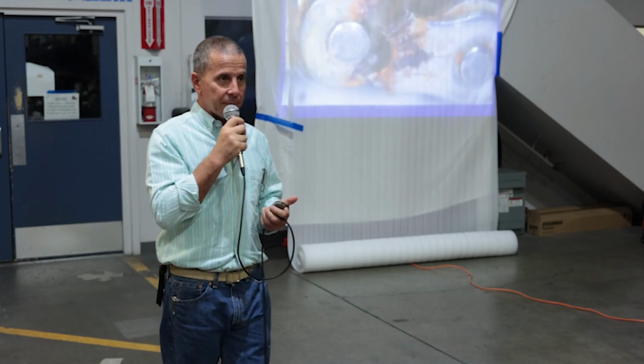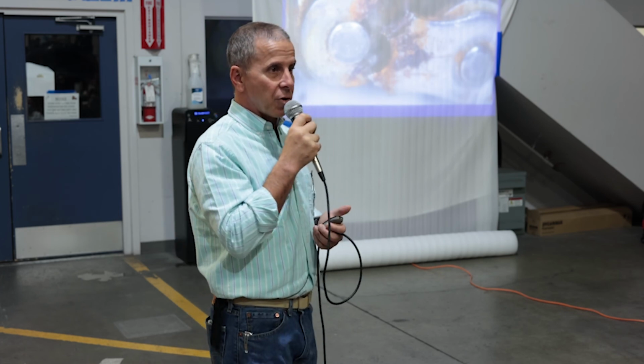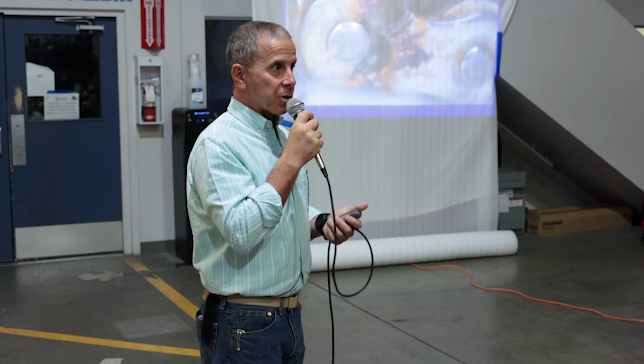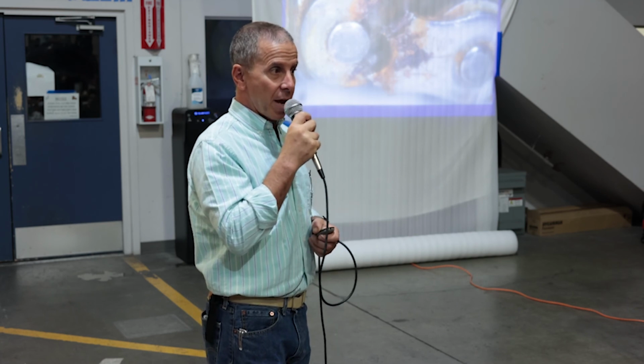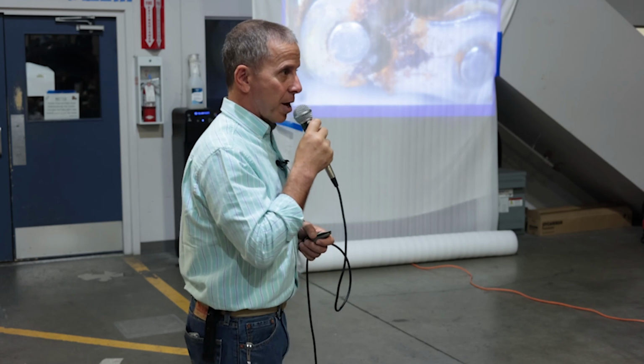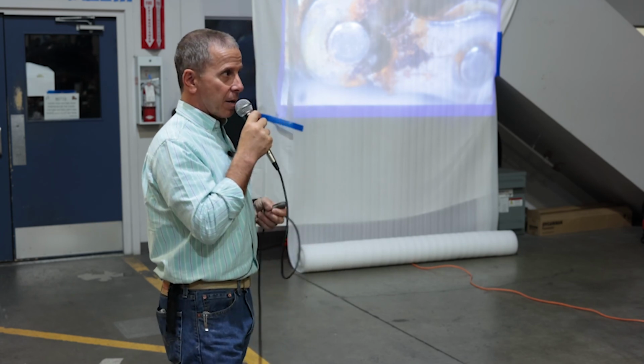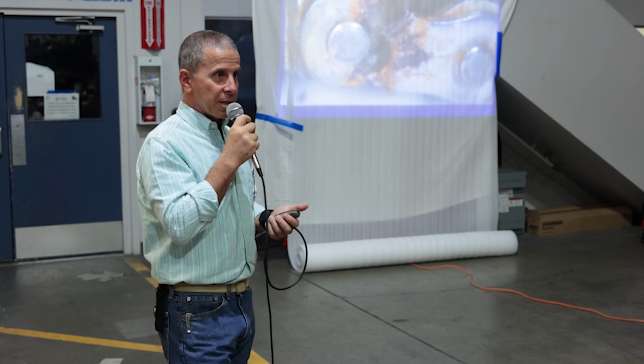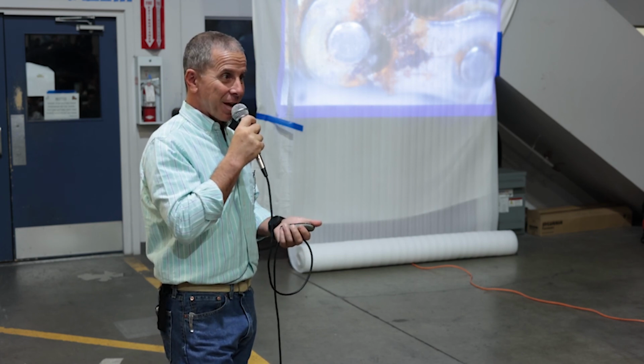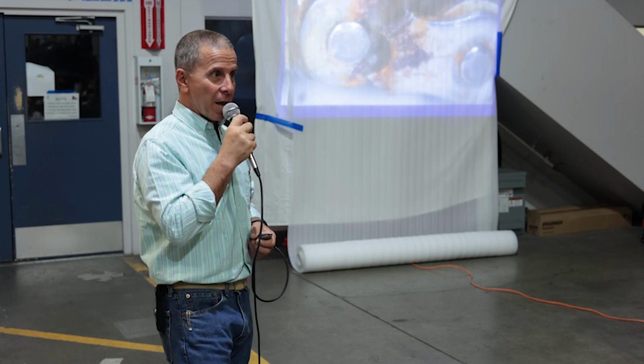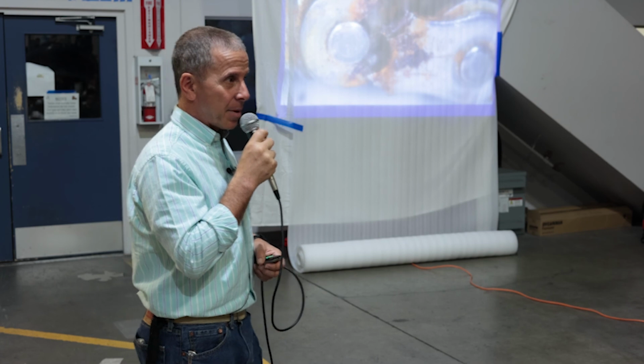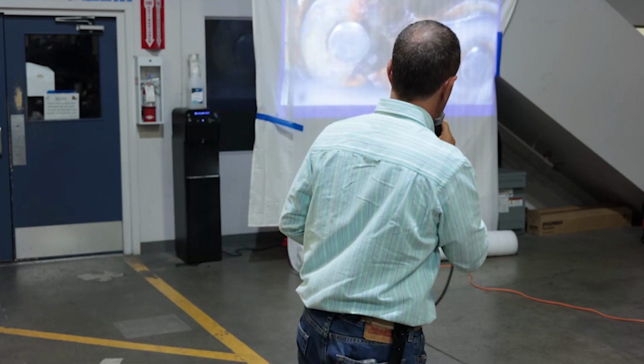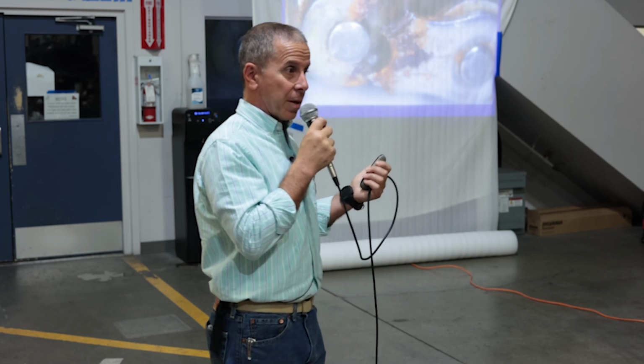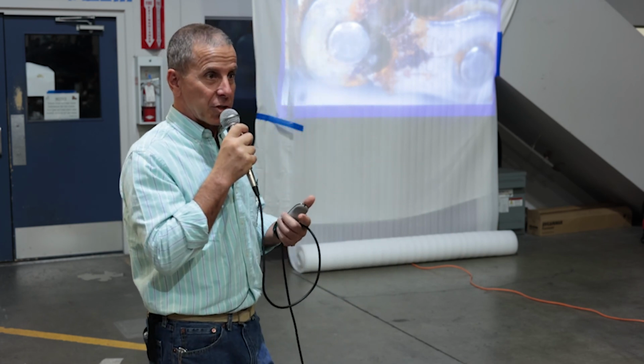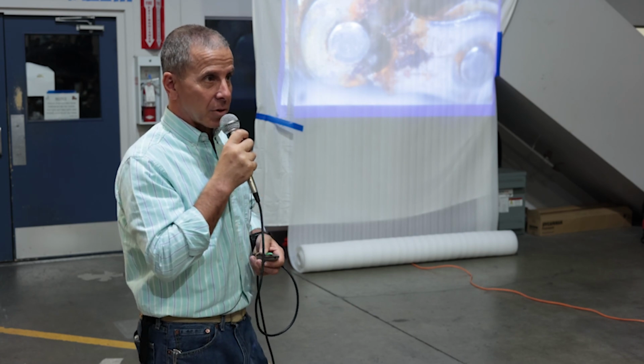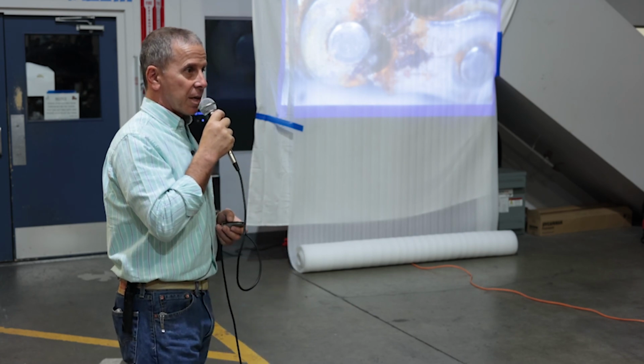Stainless steel is also susceptible to something called stress corrosion cracking. So microscopic cracks develop in stainless steel that is stressed, like in an application like this where it's a chain. That stress crack is a void. Water leaks into that void. It's stagnant once again and begins to crevice corrode and expands the crack because of that corrosion. So I suspect in a scenario like this there would have been a lot of staining before this actually failed. You'd see evidence of it and know that it was occurring.